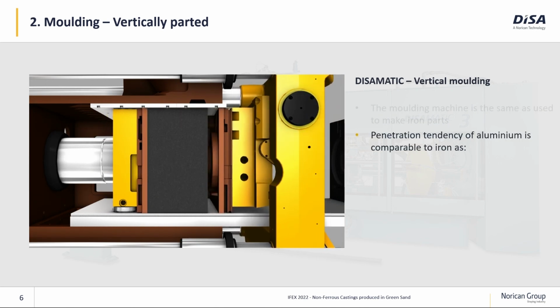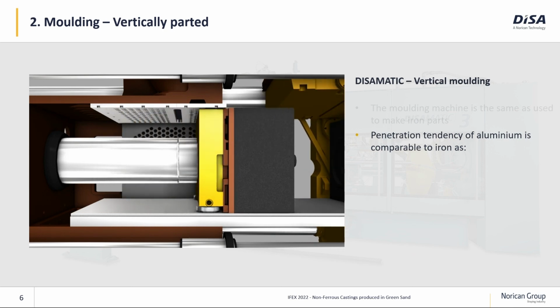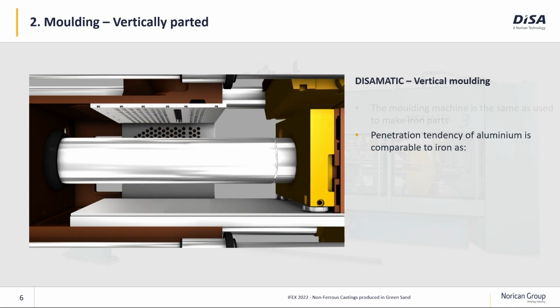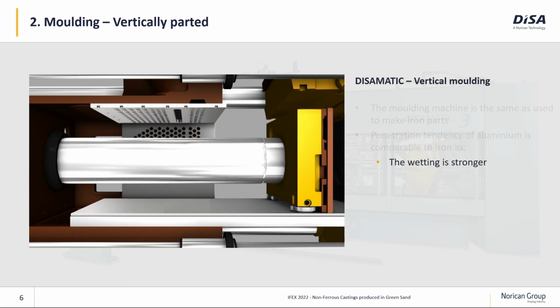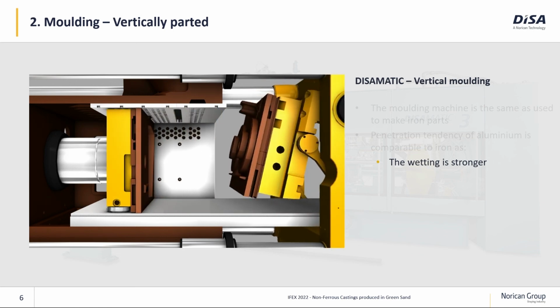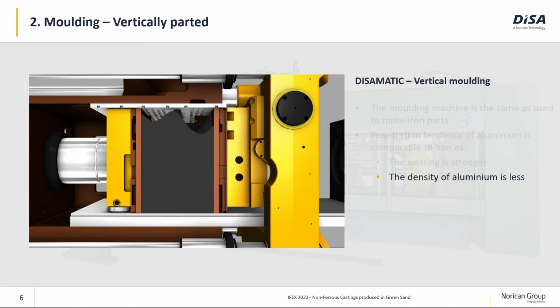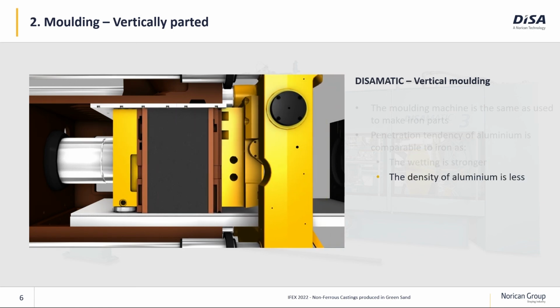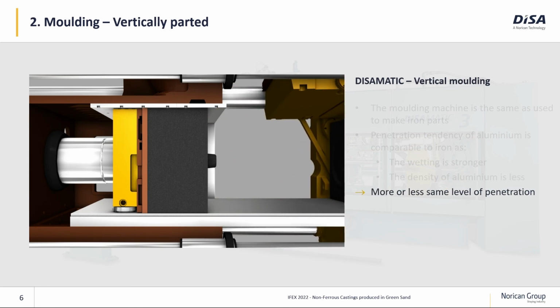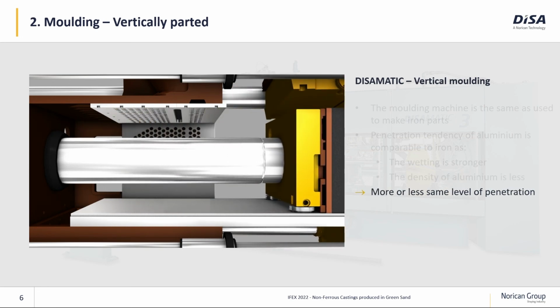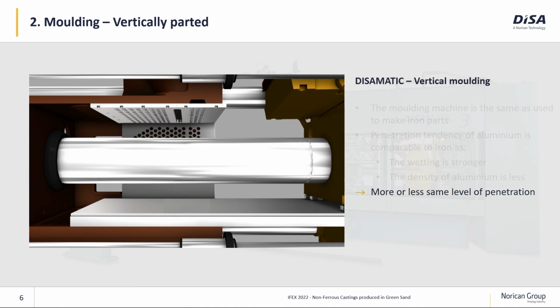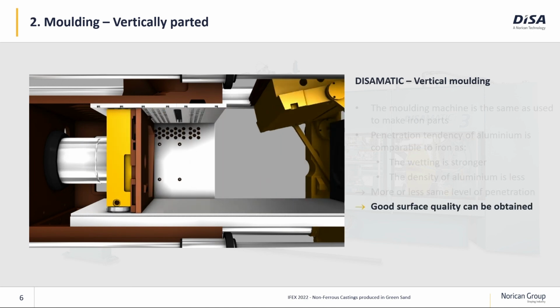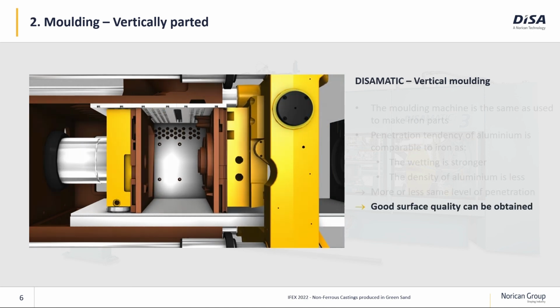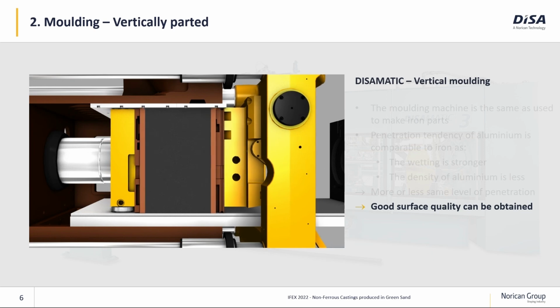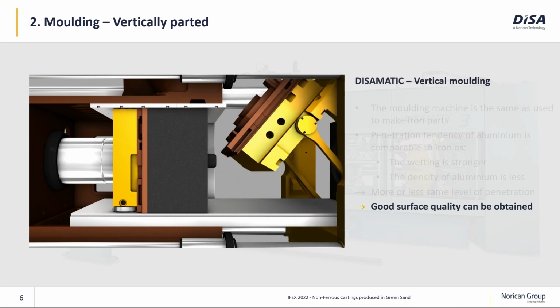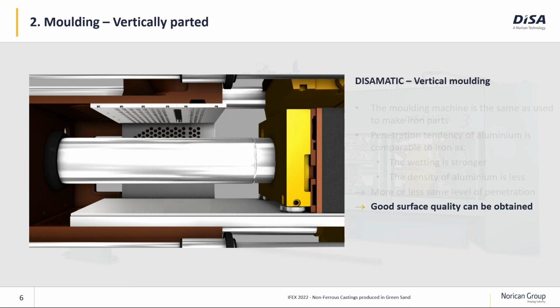If we look at aluminium, then we will see that the tendency of penetration will be more or less the same as for iron. And this is because the wetting is much stronger for aluminum, but on the other hand, the density of aluminum is much less. So at the end of the day, we will have more or less the same tendency to penetration of aluminum as we have for iron. And this means that we can get very good surface qualities of castings coming from green sand molds, even though we use sand as molding material.